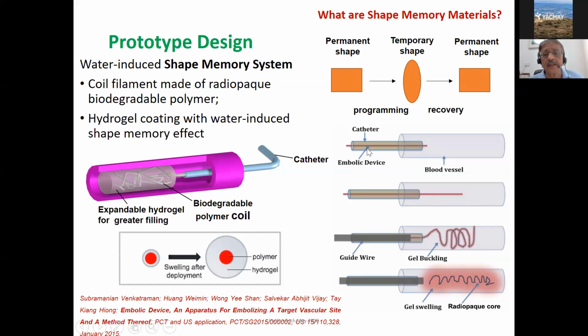Okay, so the material is inserted in the catheter as a rod of PLGA surrounded by this hydrogel, which is dried. So it's a very thin rod, monofilament, that is introduced to the blood vessel. Once it touches water, it allows for expansion. At the same time, the biodegradable polymer core undergoes what we call buckling, and that gives us mechanical strength. It anchors this plug in place, while the plugging itself is done by the hydrogel that swells and locks the entire segment, while the polymer is present as a coil to give it mechanical integrity for as long as the polymer is not degrading.